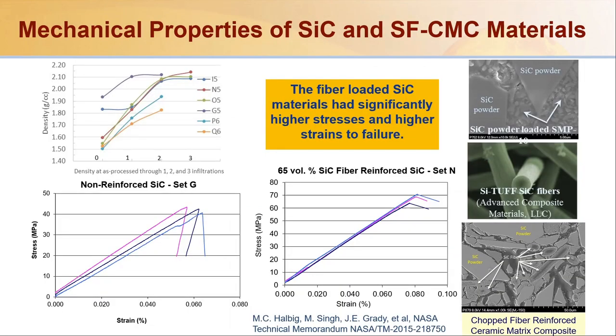In this slide, you see the density versus the number of infiltrations in these printed materials. And you can see density starts going up when you start infiltrating with the pre-ceramic polymer with some kind of silicon carbide mixture. We had done these infiltrations up to 5 infiltrations in this particular case, and we had gotten density up to 2.6, 2.5. In some recent work, we had gotten up to 2.75 in that range. But if you really want to have a completely dense material, then the other choice is you can do the melt infiltration by silicon or some silicon alloy, and you can get fairly dense silicon carbide.